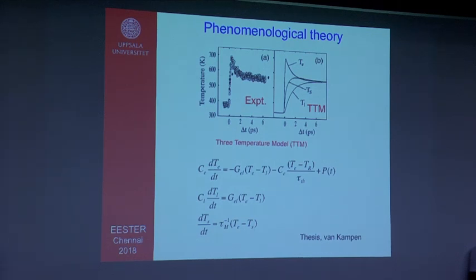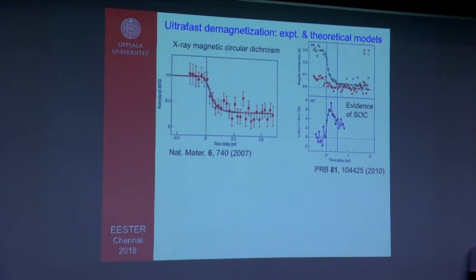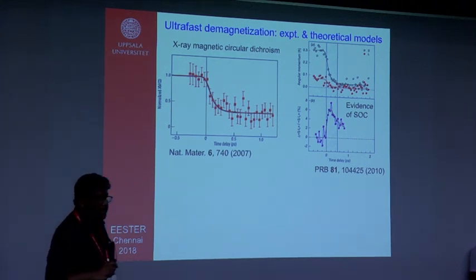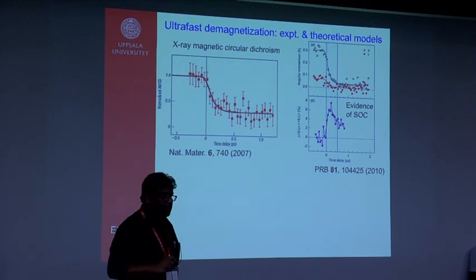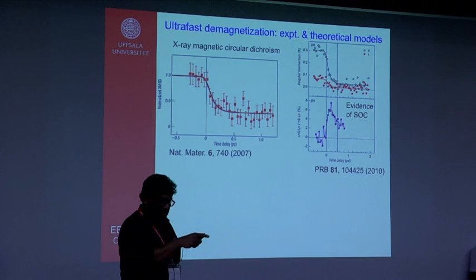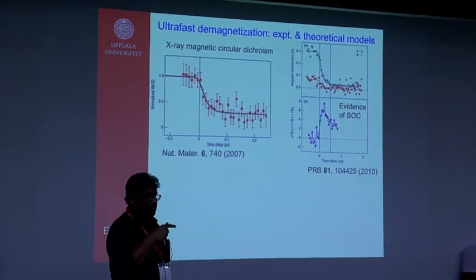Now you can do many important advanced experiments. For example, based on synchrotron-based radiations, X-ray magnetic circular dichroism, you can probe the signals as a function of time now. Many groups have done that quite recently. If you shoot very high energy ions also, they more or less interact in the same way. And there the temperature development is explained by 2 components. Spin component is not necessary.